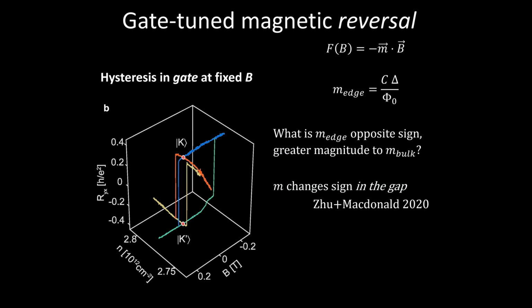But it turns out there's two ways to change the sign of this term. One is that you can change the sign of the magnetic field, and the other is you can simply reach into your system and change the sign of the magnetic moment, right? There's no real analog of this for spin, or even for spin orbit coupled systems in semiconductors, because usually the g factor is simply a number, right? It's something that's sort of set at the UV scale if you want, and it's not something that you actually can manipulate.